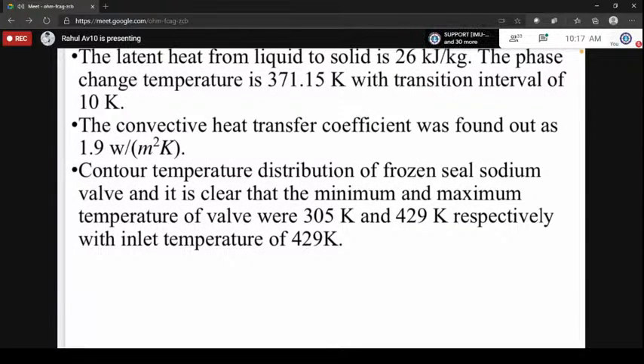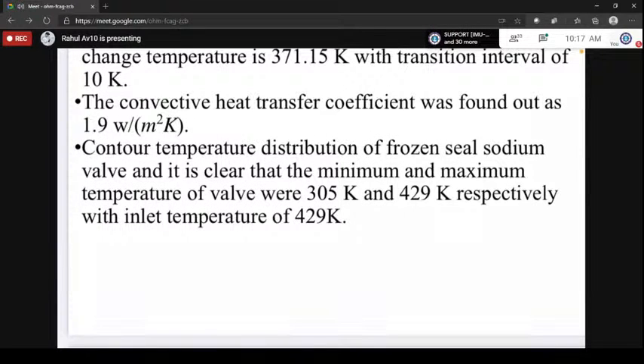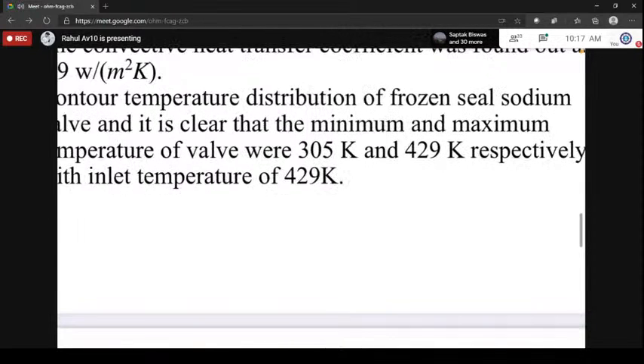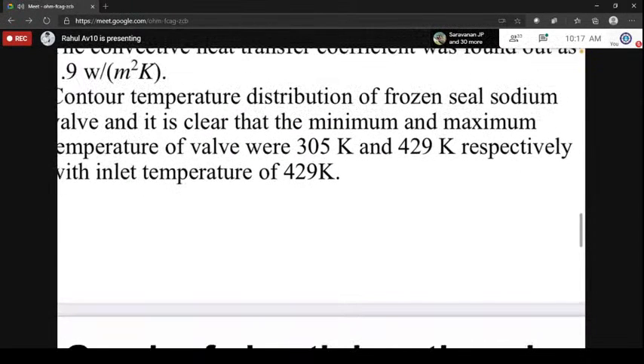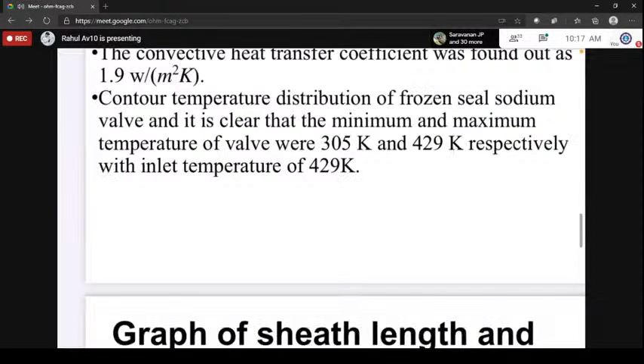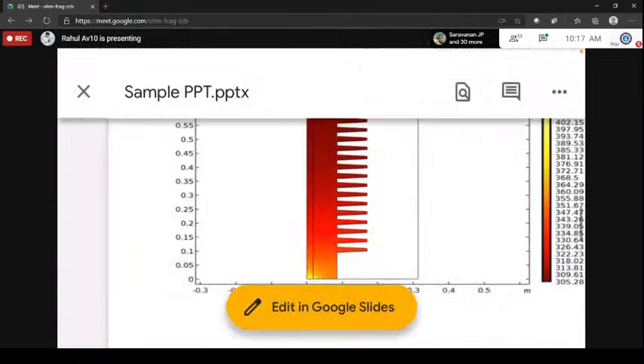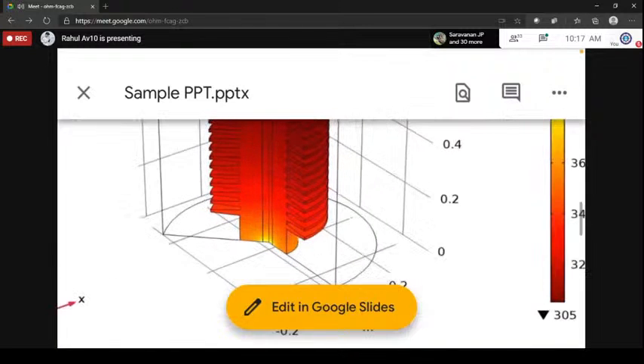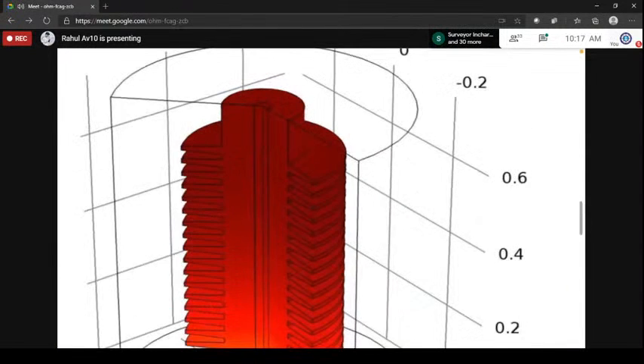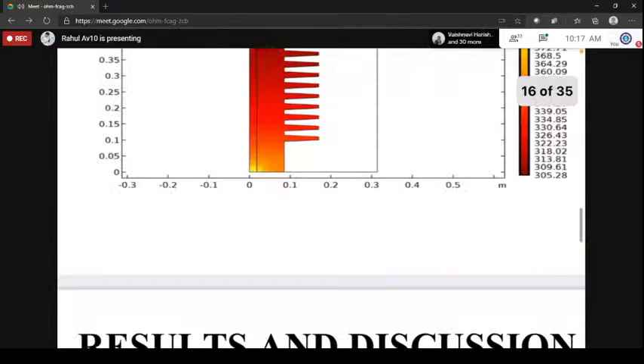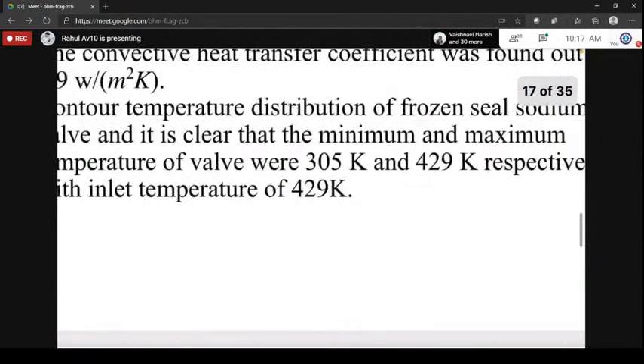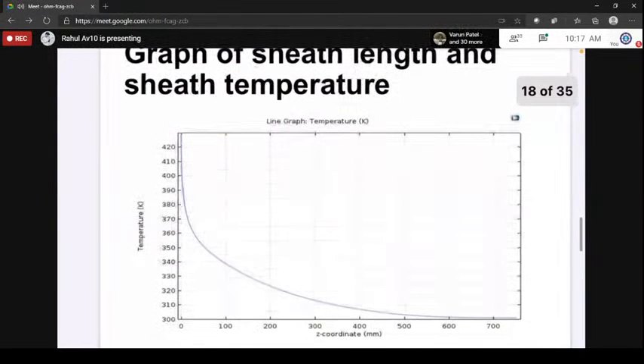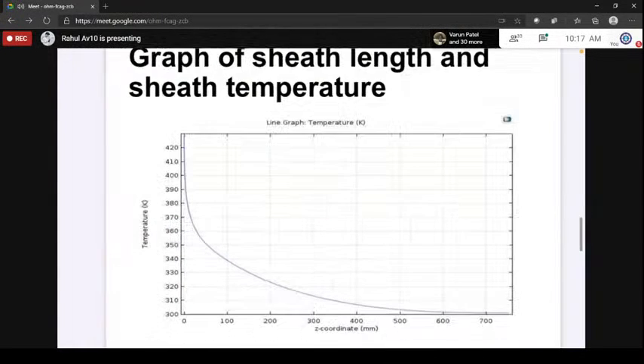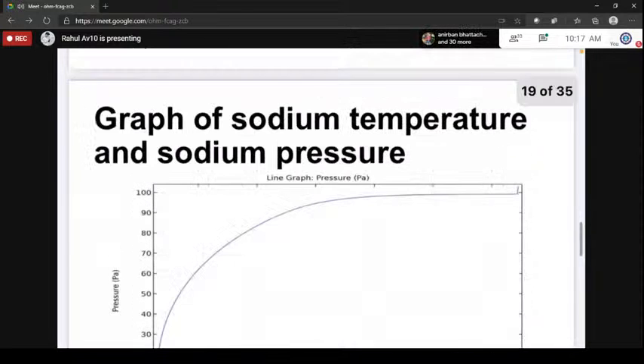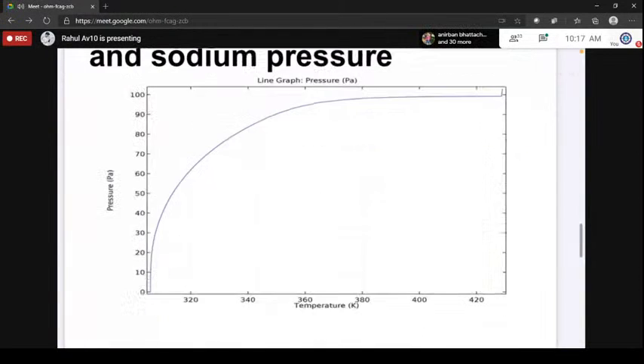And on the contour temperature distribution of the frozen seal sodium valve, it is clear that the minimum and maximum temperature, as I told earlier, are 305 Kelvin and 429 Kelvin, where 429 Kelvin is the inlet temperature, which is the maximum at the bottom of the frozen seal valve. As sodium freezing takes place, the minimum temperature in this case will be 305 Kelvin. And this is the graph of sheath length and sheath temperature in this case 1. And this is another graph of sodium temperature and sodium pressure of case 1.